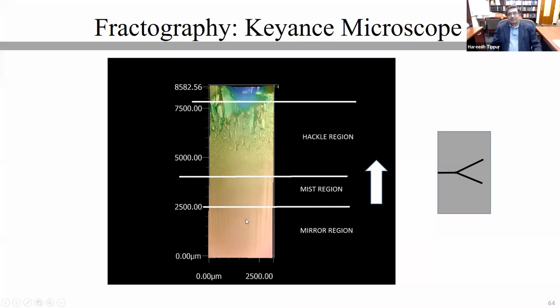Mirror region is immediately after the crack initiates from the notch itself, and mist region is a preamble to the Hackle region. Hackle region is where you see chunks of material being pulled out of the monolithic specimen itself. The fractograph here is about 8.5 millimeters long.